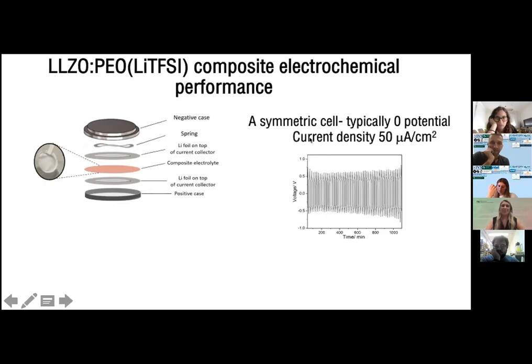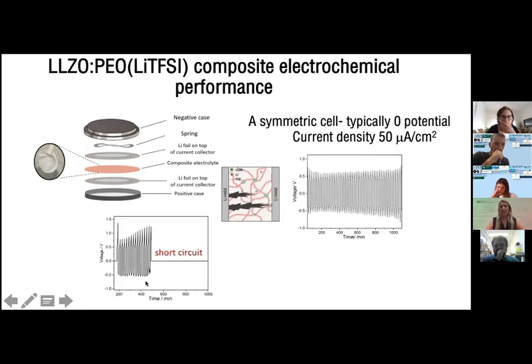So we apply a current density of 50 microamps per centimeter squared, and this is how our electrochemical performance looks like. It's very nice, it lasts for long, it doesn't short circuit, for example, as here. This is as we started to cycle it, probably one of the dendrites touched the other electrode and short circuited our cell.